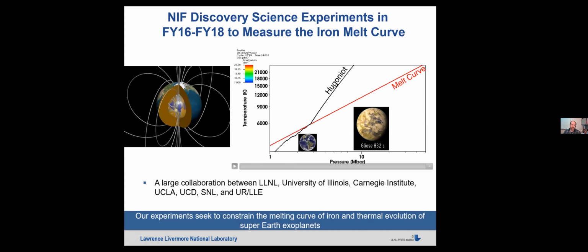So at the NIF, I'm going to show you a video of the thermodynamic trajectory we take our samples through over the time scale of the experiment. On the left is the temperature, again in log space, from about 4,000 degrees up to around 25,000 degrees. And on the x-axis is the pressure in megabar, from 1 megabar up to around 40 megabar, or 100 GPa up to 4,000 GPa.